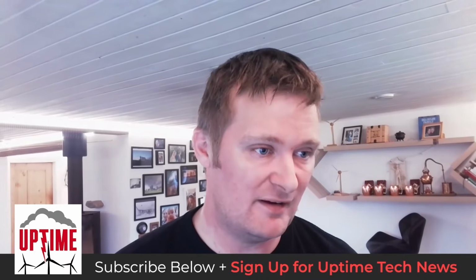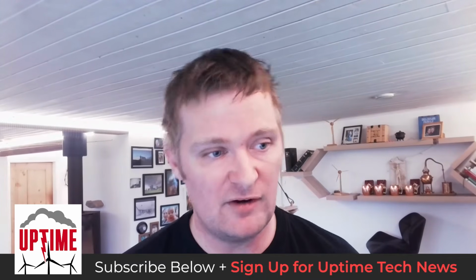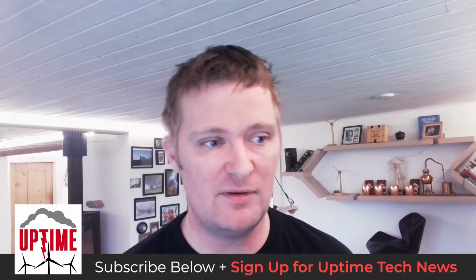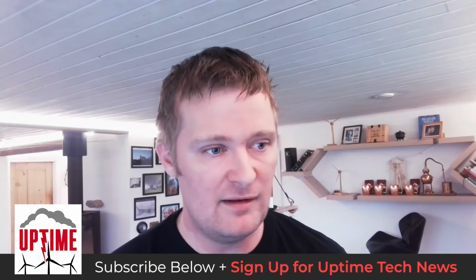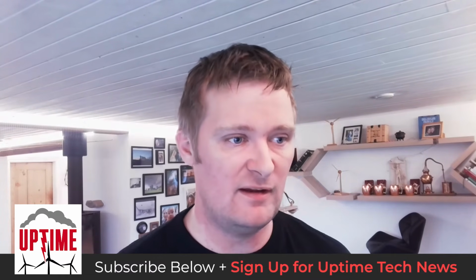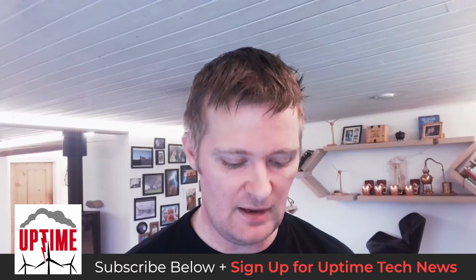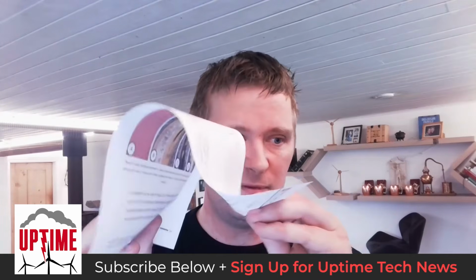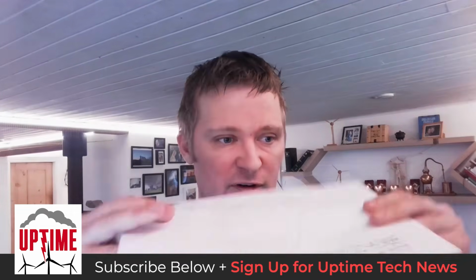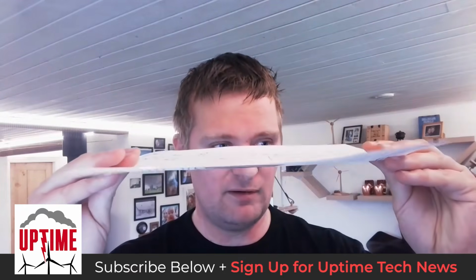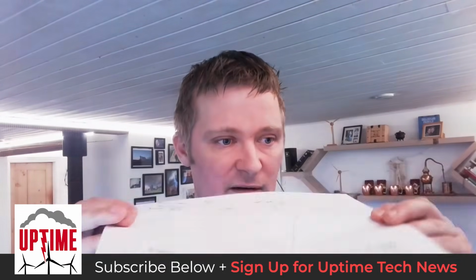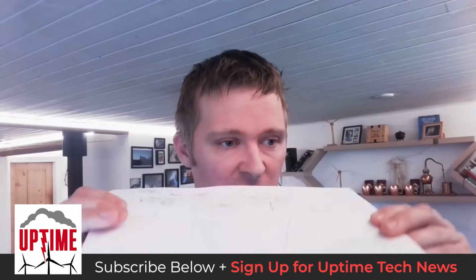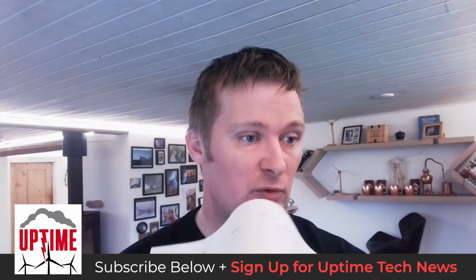Most of them are detected by the QA personnel at the factory. They're actually quite good at this, but sometimes something slips through the cracks. And one of the critical ones is a wrinkle. If you look at a piece of paper like this, if it's stretched out, this is a good laminate, because the UD fibers can hold a lot of tension and compression. So the laminate is working as it should.